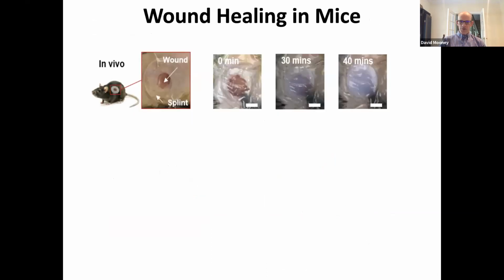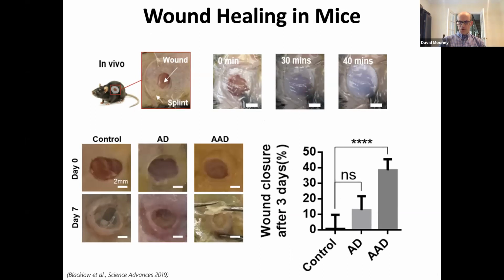So he then pursued placing these onto wounds of animals, and demonstrated that they would undergo this phase transition, they would contract, and they would exert contractile forces on the underlying tissue. If one looked at the amount of wound closure after 3 days, control animals had no wound closure. When there was the adhesive by itself, there was some minimal amount of closure, but there was significant wound closure when he used the active adhesive dressing that applied this mechanical load.